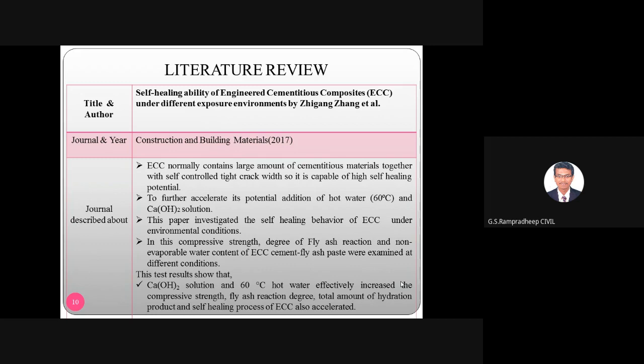So examine the different conditions. What are the observations and outcomes they are calibrating? See, calcium hydroxide solution and 60°C hot water effectively increase the compressive strength, the fly ash reaction degree, and the total amount of hydration product. So fly ash obviously reacts with that calcium hydroxide. Just see that. Why are we adding fly ash? It proves that fly ash reacts with the calcium hydroxide in the presence of 60°C. Again, it forms a good quantity of hydration product. Automatically, the self-healing process is also accelerated, so your bridging is tight enough, right? So finally, they have proved it.